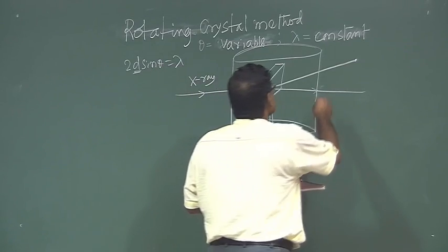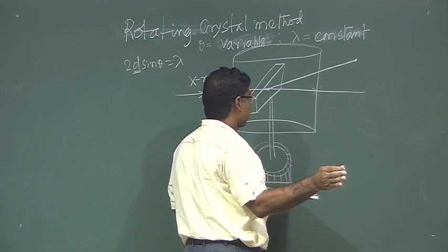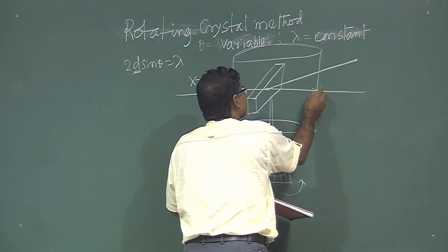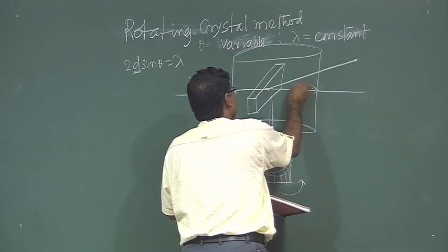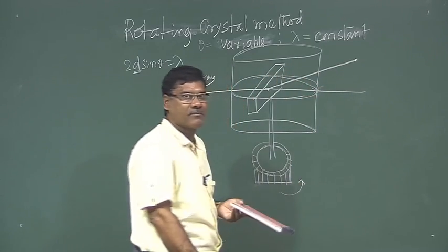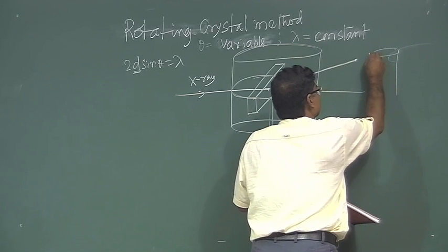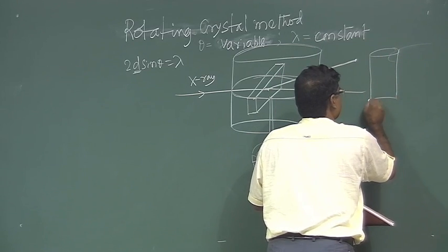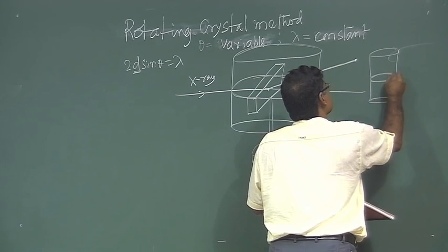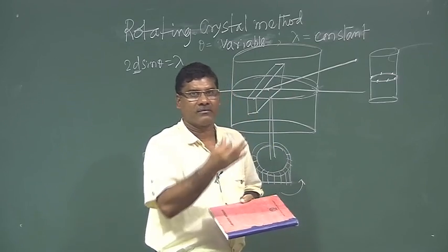So here basically for these planes in a zone, if I draw here, you will get all spots on this circle, right. Okay. So it will be on this circle, this horizontal circle. So these are spots on this circle. So this will represent different planes of that zone.